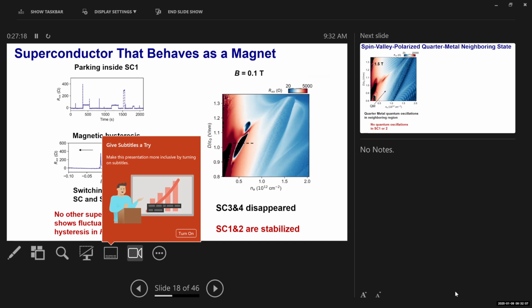So what we think may be going on is that when it switches, there has to be a domain wall moved in, and if that domain wall is trespassing the path from source to drain, the domain wall could be resistive. Especially in this case, if these two superconducting states correspond to opposite valley polarization, then this tunneling across the domain wall has to violate momentum conservation, and that has to be resistive. But wouldn't it be easier for the superconducting regions to find a circulation path around this? I think what you can see here is when the domain wall really cuts through the path completely, there may be cases where the domain wall is in parallel with the current, and your supercurrent still shorts everything, and you wouldn't even see a resistance fluctuation or deviation from zero in that case.